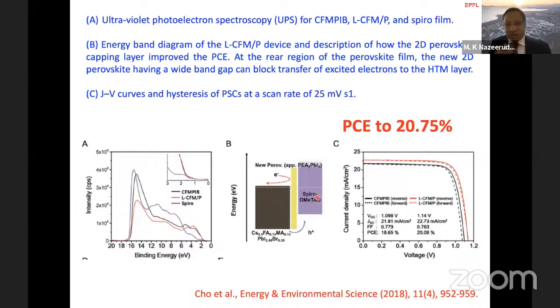How do we know that this is happening? Let's take the IV characteristics of these materials. So take the reference sample, which has a VOC of 1.09. This is the open circuit potential of the reference sample. After depositing a two-dimensional perovskite, the open circuit potential has increased to 1.14.